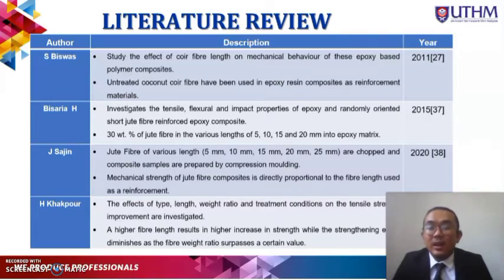Sajin conducted an experiment in which jute fiber of various lengths from 5 to 25 mm was chopped and composite samples were prepared by compression molding. The mechanical strength of the jute fiber composite is directly proportional to the fiber length used as a reinforcement. Lastly, Khakpour conducted a study where the effect of type, length, weight ratio, and treatment condition on strength improvement was investigated. A higher fiber length results in a higher increase in strength, while the strengthening effect diminishes as the fiber weight ratio surpasses a certain value. From this literature review, I have found a few parameters that can be investigated for their effect on the composite.